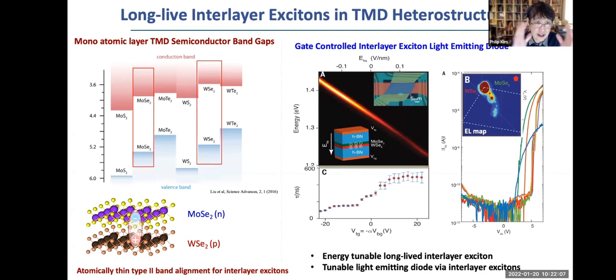Indeed, in the past few years, we've been realizing these heterostructures, atomically thin PN junctions. And once you shine light, you can create this interlayer exciton, forming electrons and holes in opposite layers of the TMD. They live quite long because, again, it's very similar to the interlayer exciton in semiconductor structures. They are living in different layers, so they don't recombine fast. Lifetime can be controlled by the gate voltages. Furthermore, the energy level can be controlled by gate voltage by applying an electric field.